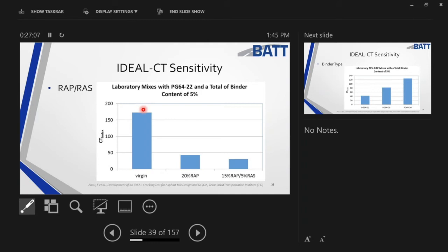That's the kicker that's really hard for DOTs to wrap their hand around or arms around in order to try to match field with laboratory. And I really see CT going forward as a lab design and a field acceptance value that may end up being a little higher. So again, important to always, even though it takes longer, guys, it's important to make sure we condition properly.